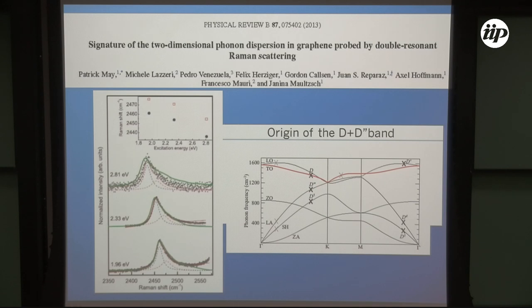Those peaks are what we call combination mode peaks, because we have phonons with the same wave vector, but from different branches, meaning different frequencies. So we have a combination of a phonon from here and a phonon from here in this case. We can have several other combinations, but in this case, we have what we call a D phonon and a D prime prime phonon. With this, we explain it, because if we take the K-gamma direction or the KM direction, for the same branches the frequencies are very different. You can tell just by looking at this page. You have this frequency with that, or this frequency with that, and the frequency of the band will be different. So that's the reason we did the calculation.